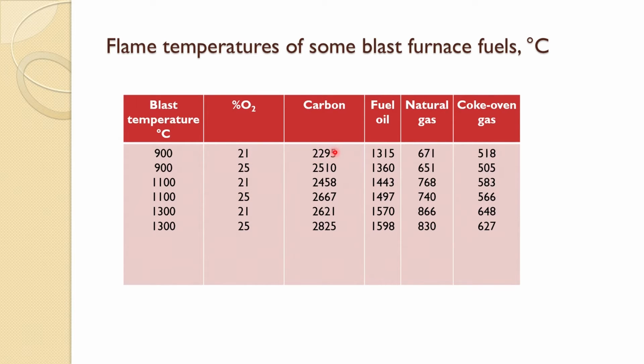Now, instead of carbon, if you are using fuel oil, see how much the flame temperature decreases, very low. And natural gas is even lower, coke oven gas is even lower. So, probably these are not even correct to use, and may create more problems, more volume and so on in the blast furnace. One has to look at the whole chemistry and the volume of it, and then use the right combination or right fuel.